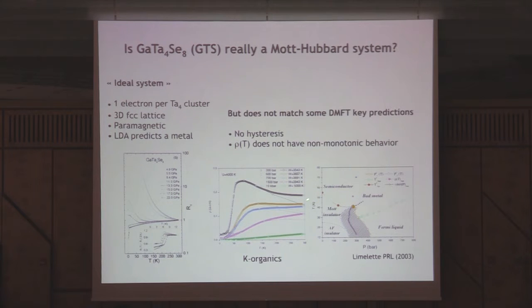You see that the system is, when you're just in the correlated metallic state, when you come from high temperature, the system thinks that it's an insulator, but suddenly you hit the onset of coherence when the quasiparticles are formed, and immediately you go down to a very nice Fermi-liquid state. So neither the coexistence region with the hysteresis nor this non-monotonic behavior was observed in these samples.